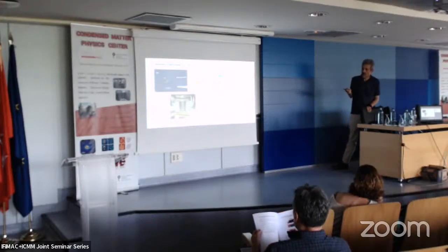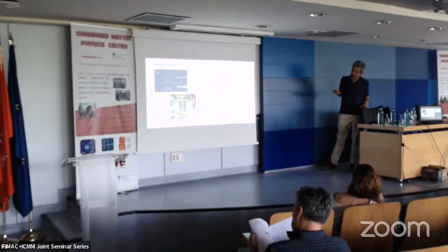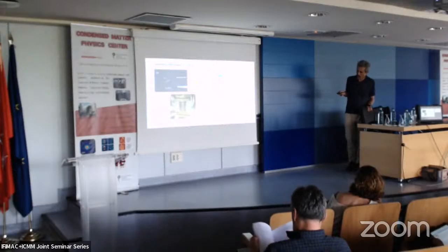So to solve these problems, we devised a new method of measuring the resistance, but also the thermoelectric temperature of the wire. So we were measuring several signals at the same time. And this has several advantages that we will see. You can see here the 2 Wollaston wires soldered at the end. This is the tip. And from the thermoelectric properties, you can get the temperature right there. So you know what temperature you have just by measuring the DC voltage that develops between the 2 wires. We can use this wire as a tip and scan with it, as you will see.